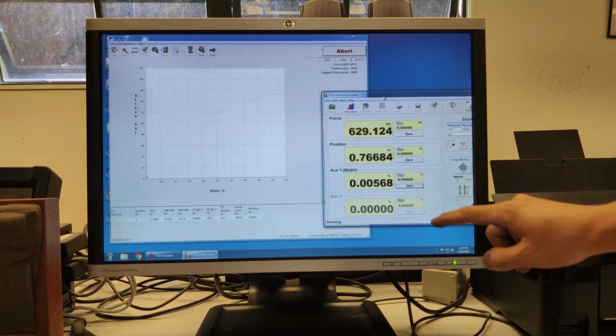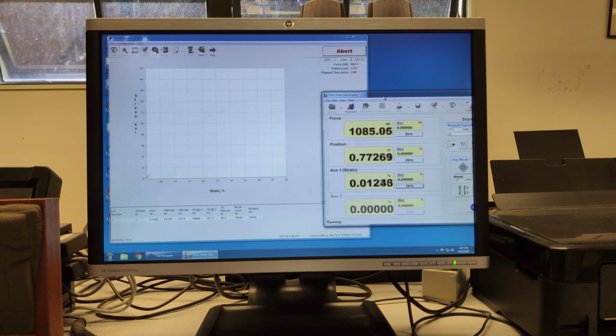Now, all the values on the indicator keep increasing. It shows that the testing frame is lifted upwards, so the position value is increasing. Then this movement of the testing frame generates more load, which is stretching the sample. Therefore, the strain is increasing too. On the plotting window, we can see the stress-strain curve is generated by the software now. The straight line is the calculated modulus, the slope.